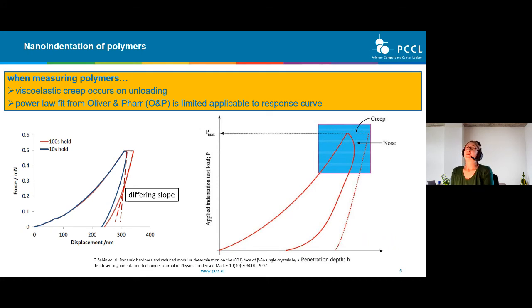So what's now so specific about nanoindentation of polymers? When we do nanoindentation of polymers, we have viscoelastic creep on the unloading curve. And the power law fit of Oliver and Pharr, which I explained before, is only limited applicable to this response curve. You can see it very well on the left on the slide, where we do nanoindentation in the same material, but with two different holding phases. One is a 10-second holding phase, and in red, we have a 100-second holding phase. And we get two different unloading curves. And from these two different unloading curves, we would get two different elastic moduli. But this can't be true. And on the right side, you can see a typical nanoindentation curve in a viscoelastic polymer. Without a holding phase, you see this typical nose building, which leads to a wrong elastic modulus.